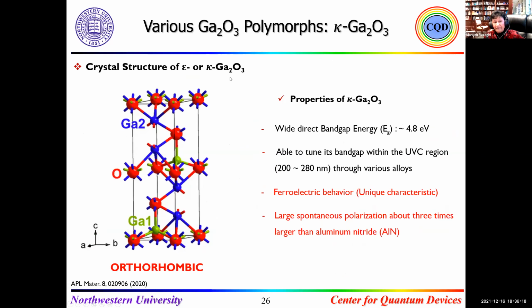The kappa phase is a wide direct band gap of 4.8 electron volts, but is able to tune its band gap within the UVC region through various alloys with indium or aluminum. It also has the unique characteristic of ferroelectric behavior, with spontaneous polarization about 3 times larger than aluminum nitride, and orthorhombic symmetry.